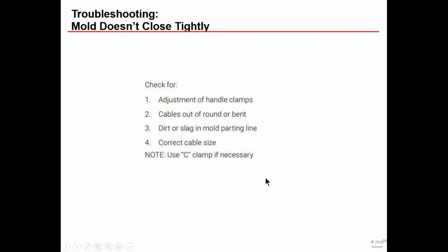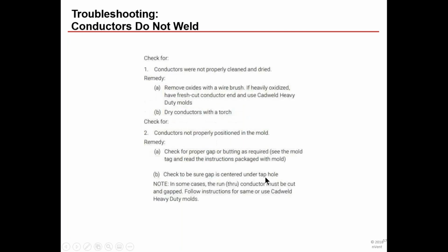That definitely will keep you from creating a proper weld. Conductors do not weld. So you'll need to look at if they don't weld properly. You need to make sure that you did go through your cleaning process and properly clean them and dried them. Again, using that wire brush and a torch will help you there in getting those prepared. Also make sure that they're positioned correctly. If they're out of position, you could, again, create that hole in the middle where all of your weld will sit in the middle and barely attach to your conductors and does not provide for a good weld.